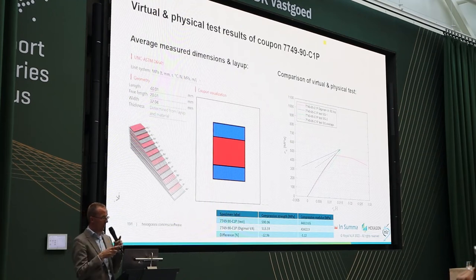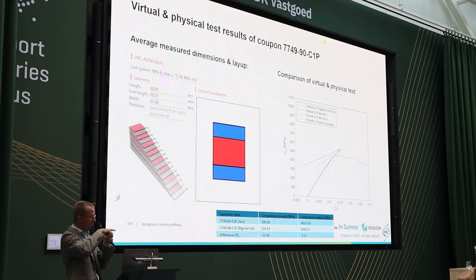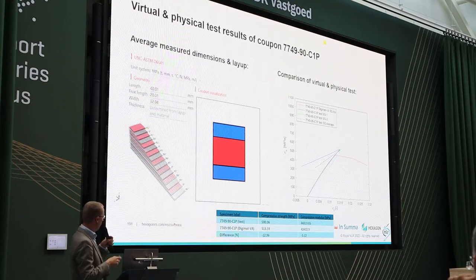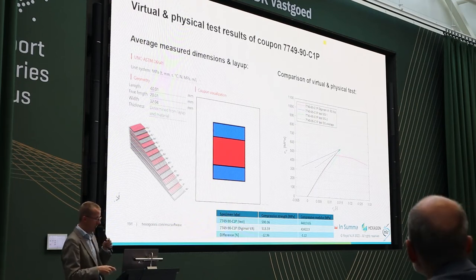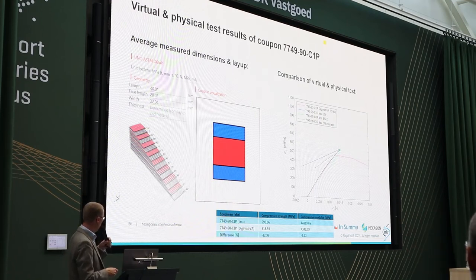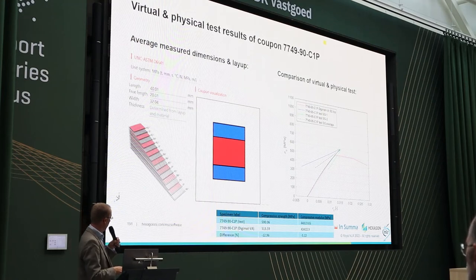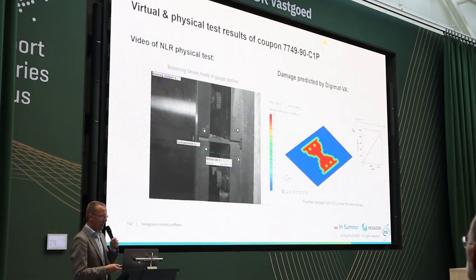After a certain point, the coupon fails, but also the strain gauge, and the signals go diverging, and then the strain gauge is also broken. So the black line is the average of the two back-to-back strain gauges. If I compare the Digimat results, the stiffness is very accurate, like 3% underpredicted, very nice. The compressive strength is like 30% different, so a bit underestimated, but all in all, it's quite good, I think. Room for improvement always, of course, but not unsatisfied.